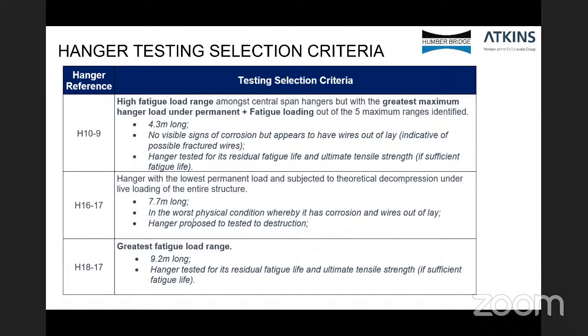Hanger 16-17 is the hanger with the lowest permanent load. As I've shown earlier, there was significant variation in load, and if the entire bridge was loaded, then it was subjected to theoretical decompression under live loading. It was 7.7 meters long. It was in the worst physical condition, whereby it had corrosion of wires and wires out of lay. It also had water seepage from the hangers. It was proposed to test this hanger to destruction.